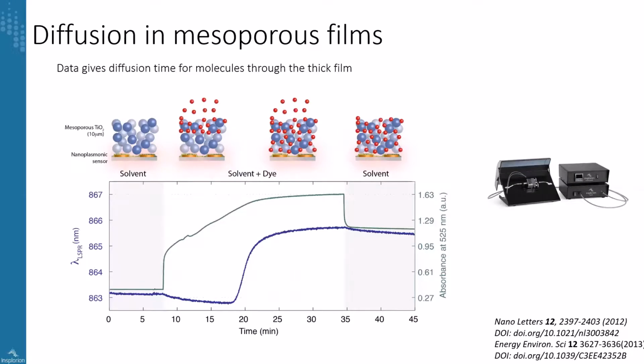In this case, because we were using an organic dye that has its own absorption peak that doesn't overlap with the plasmonic peak, because the dye has this color and we're tracking 525 nanometers, which is the peak of absorbance for this dye, we know that after the 8th minute, the dye reached the measurement chamber of the system. And you can see this by the increase in the green graph that is very quick and very steep. But you can see that it keeps increasing over time, which gives you a hint that it might be penetrating through the film until it reaches almost the saturation.